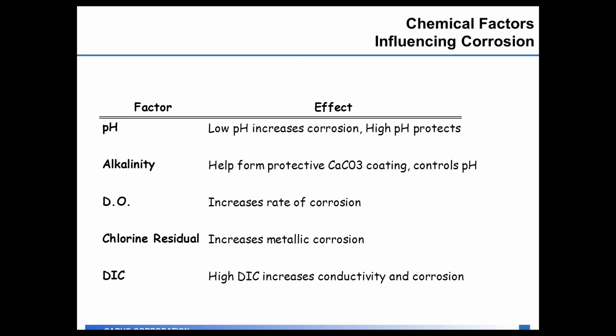Finally, one of the last things that many states are adding to their corrosion control chemistry is DIC, which stands for dissolved inorganic carbonate. It's a measure of a lot of different factors in your distribution system, and a high DIC increases how conductive your water is and would actively prevent corrosion control techniques. What that means is you might have to feed more phosphate or have a higher pH or a higher alkalinity to try to combat that high DIC interference with your corrosion prevention.